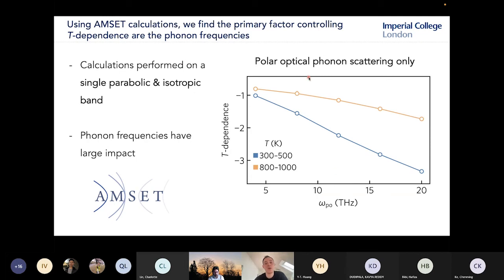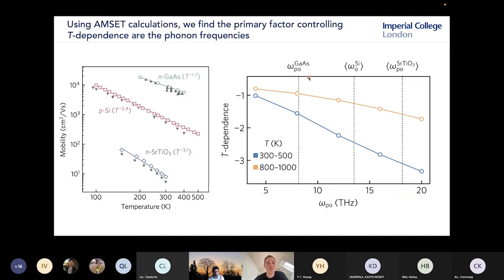Now, I mentioned this is only polar optical phonon scattering. I hope I can convince you that we believe the phonon frequencies are actually responsible for the temperature dependence in all types of phonon scattering. So here I'm going back to this summary plot of gallium arsenide, silicon, and strontium titanate. Gallium arsenide has a polar phonon frequency of about 8. If we read off about 8 on this plot, you would expect a temperature dependence of about -1.8 or -1.6. And that's really close to what we see in experiment, -1.7.